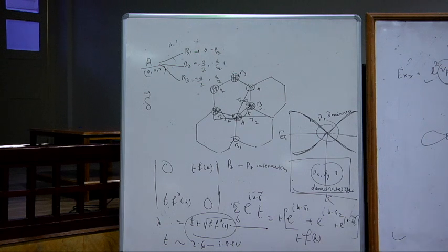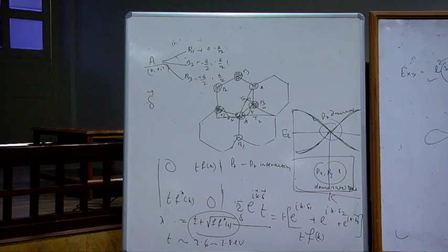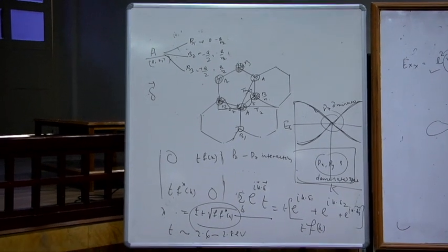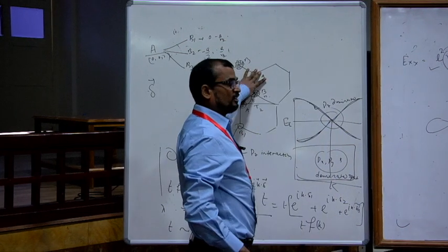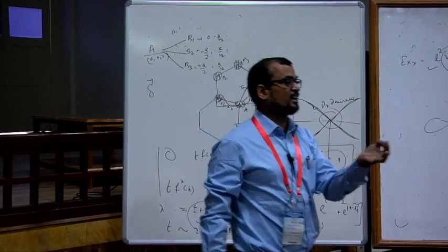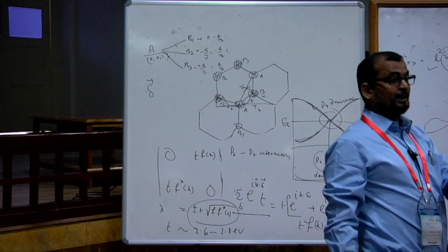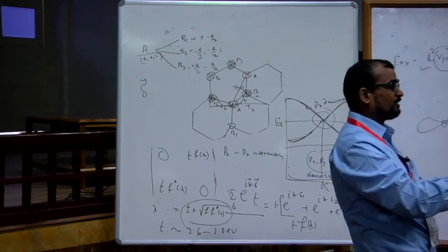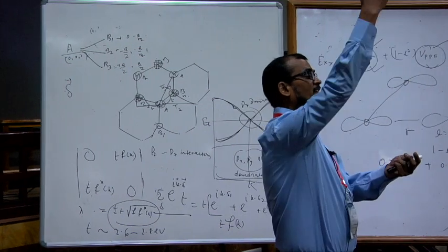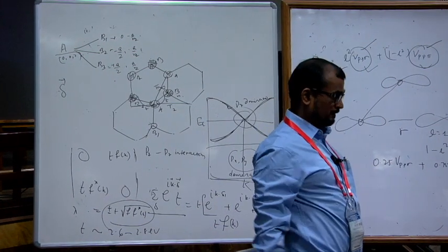Then you say that these states do interact with each other with certain interaction energy. And it has been identified that if you go from first neighbor to second neighbor, the interaction energy is hardly 0.2 electron volt. It gives you the physical picture. Yes, my interaction is very strong at the nearest neighbor level and vanishes as I move forward.